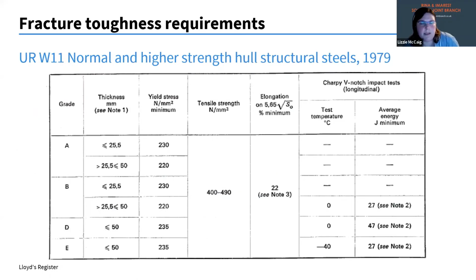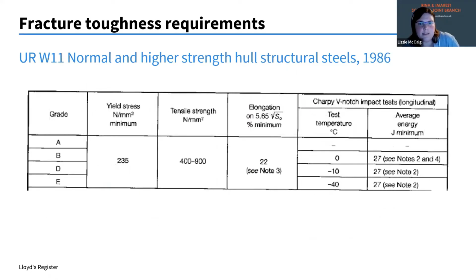But we can look here. In 1979, as you can see, we've got some requirements for these grades, but we don't have anything for A and B. And this is looking at IACS UR W11, which provides the standard for hull structural steels. By 1986, we've got a few more. We've got an average energy requirement here. We've got a test temperature requirement. Still nothing for grade A.